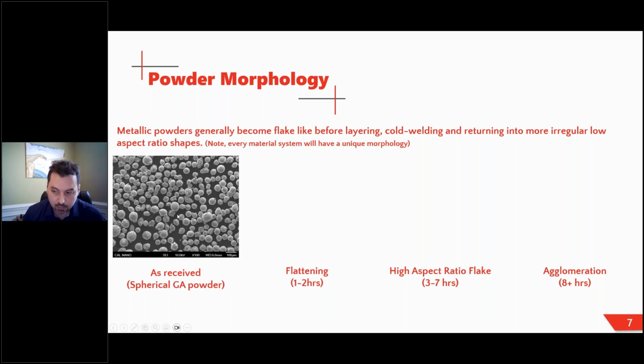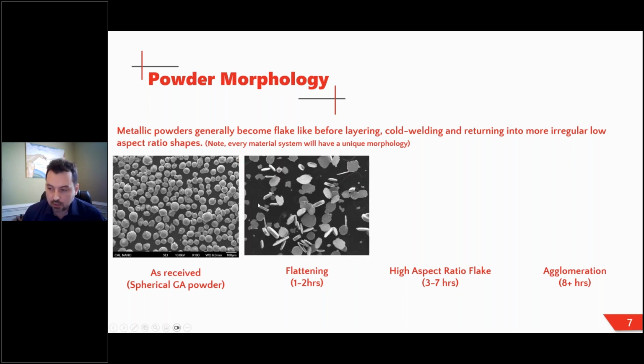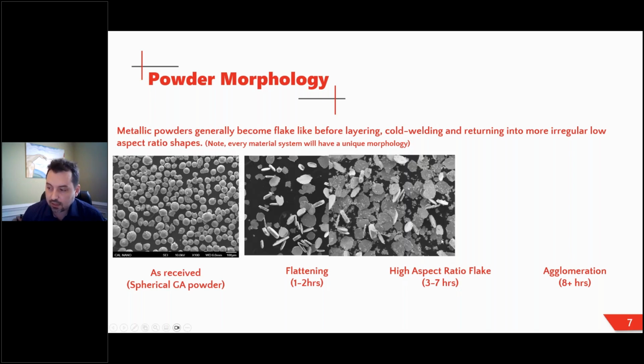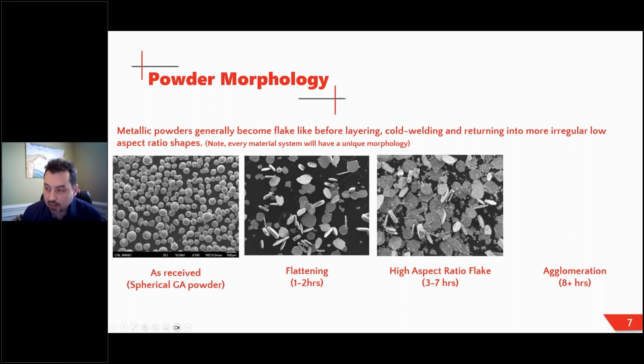But this is just an example for a light material, an aluminum in this case, that started off with spherical atomized powders. As we start to mill, those powders are going to get compressed and smashed in between those balls, like I mentioned, and they're just going to pancake out as you'd expect. In the first half hour to hour, they're going to start to look like kidney beans, and then they're going to start to flatten out into these flakes. Then as the milling continues, that flaking aspect ratio is going to get higher and higher, thinner and thinner sheets. And then as those sheets start to stack on top of each other, they're going to be cold welded together.